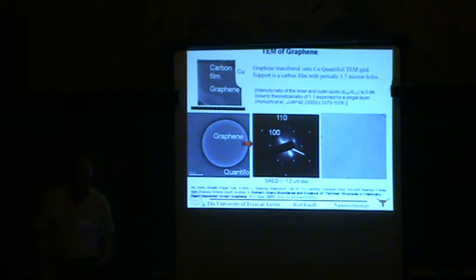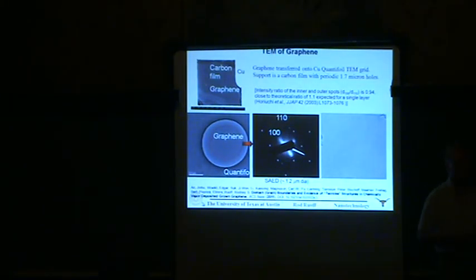and then go to high resolution. What's been quite interesting is the assignment of misorientation angles, and they cluster around certain angles. This has just started, and it's very challenging. Understanding the atomic scale structure is something that will be heavily researched in the future, and I envision, in terms of mechanics, that there will be the use of these sorts of nano-lab manipulators inside of TEM, where you've created a defect of a certain type, perhaps by knocking out an atom, or putting a small notch at the edge, and then pulling, and seeing what happens with the mechanics, including at the grain boundaries.